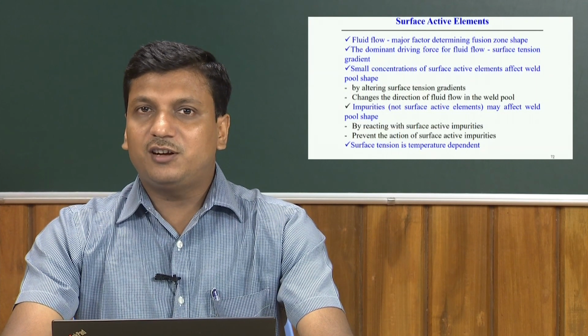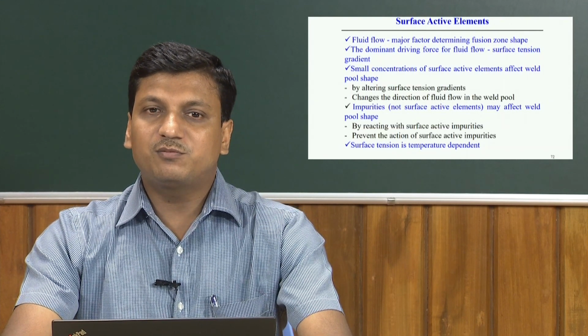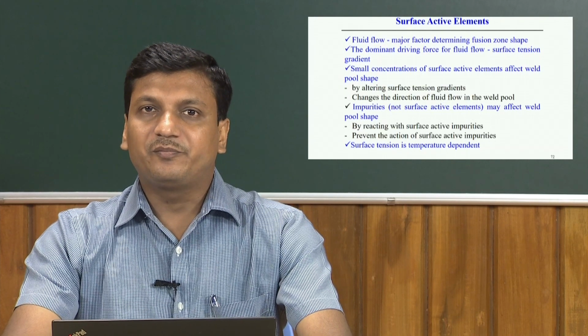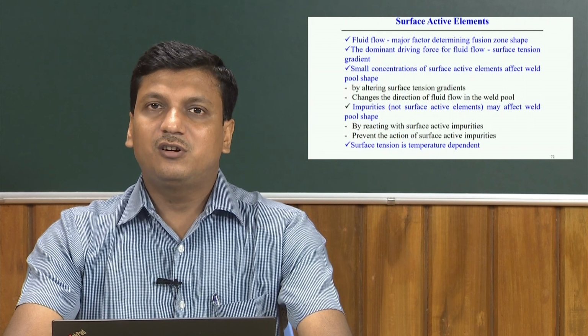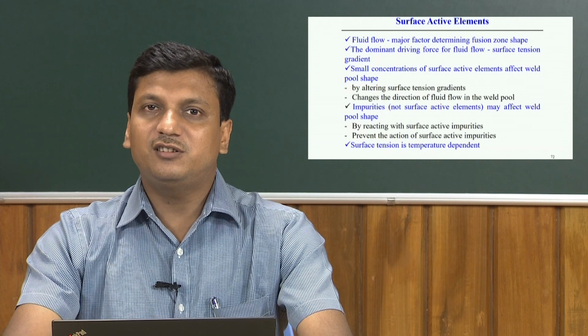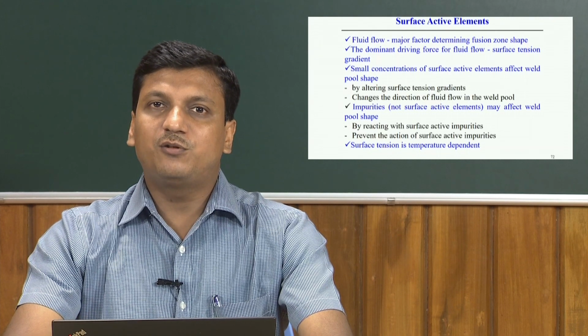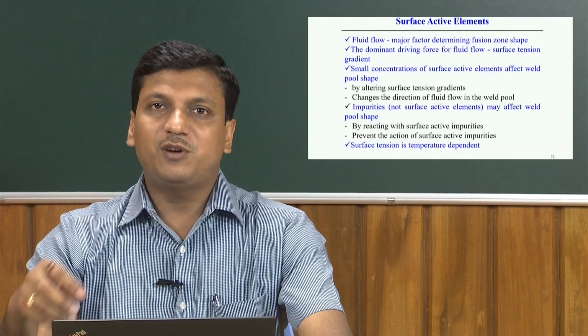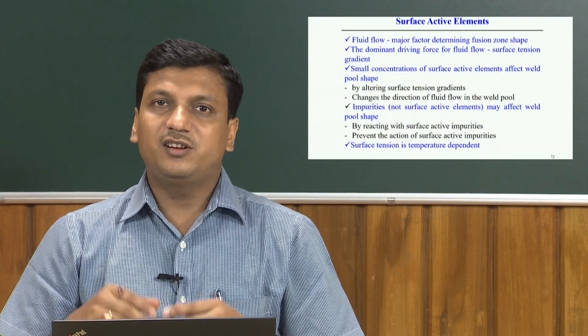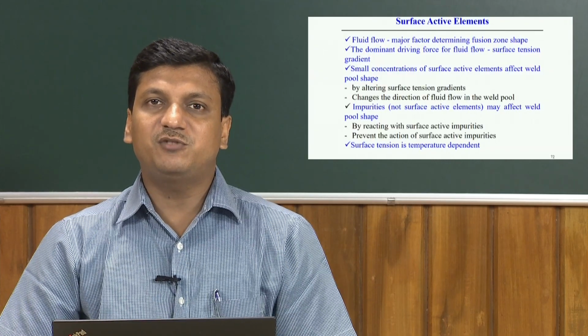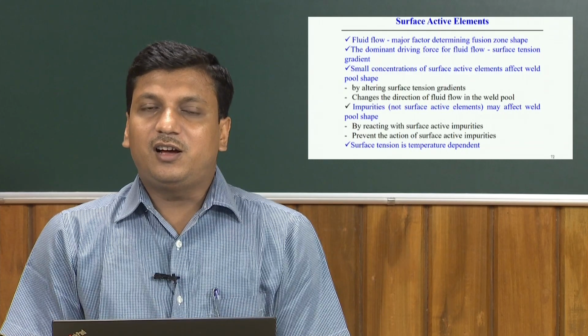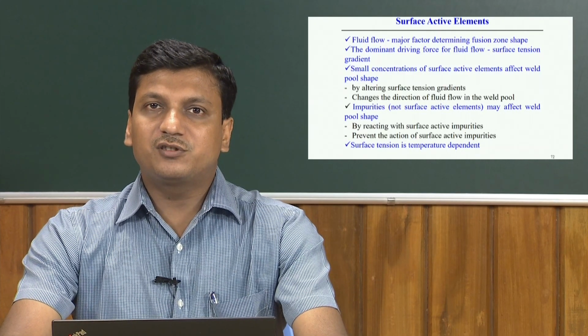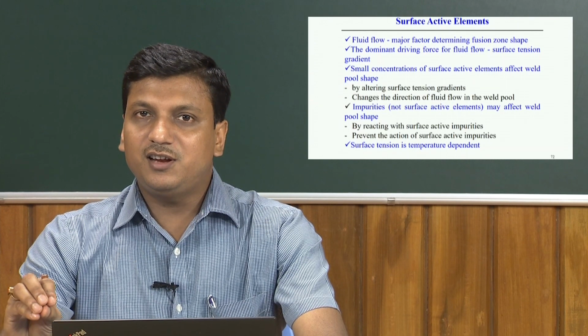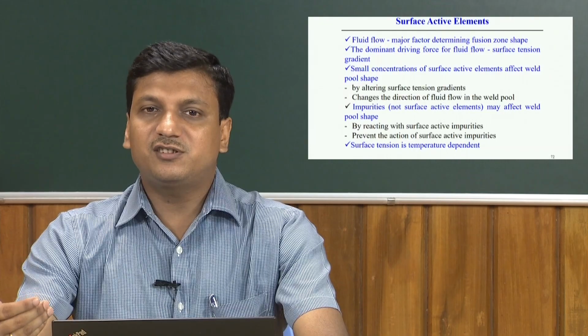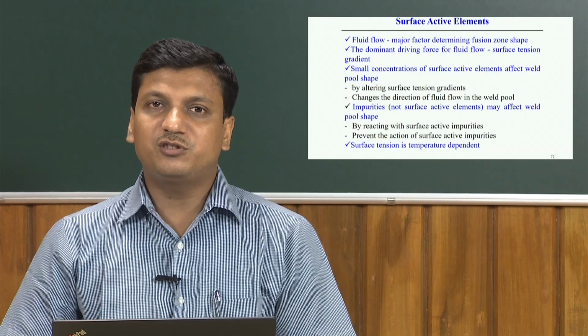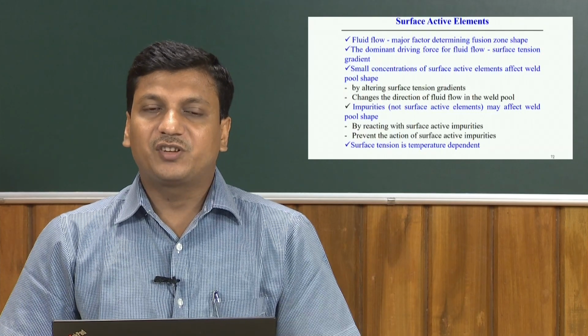So, of course, the main driving force for the fluid flow is the surface tension force, apart from the buoyancy force, or, in an arc welding process, there may be the effect of the electromagnetic force, or the effect of the plasma force that comes from the creation of the arc. But the influence of the plasma force, buoyancy force and electromagnetic force may have less impact on the material flow, while surface tension force is the most important and most significant driving force that impacts the material flow.